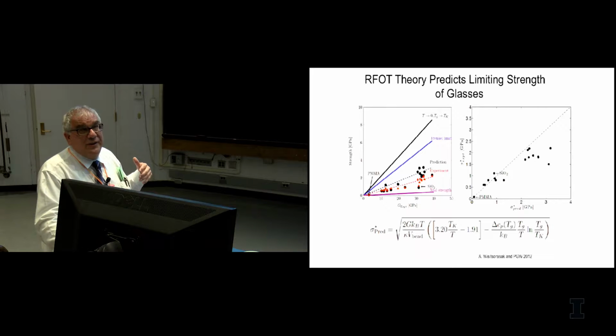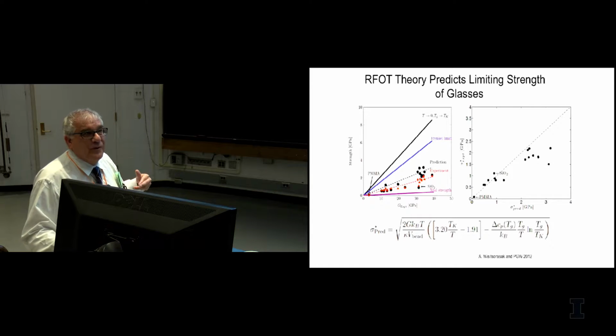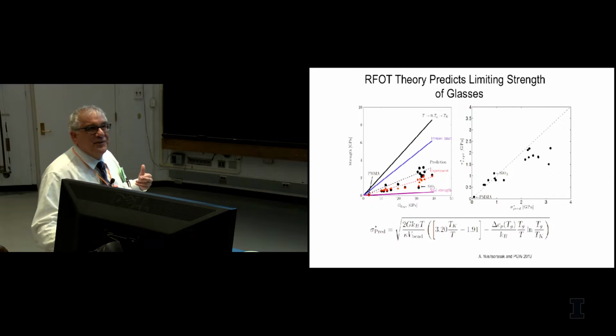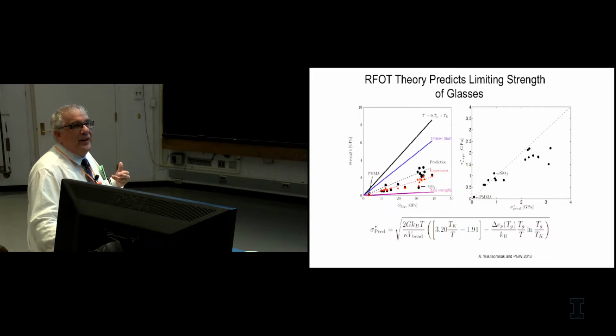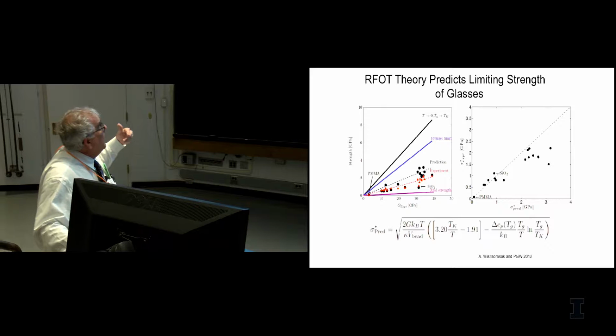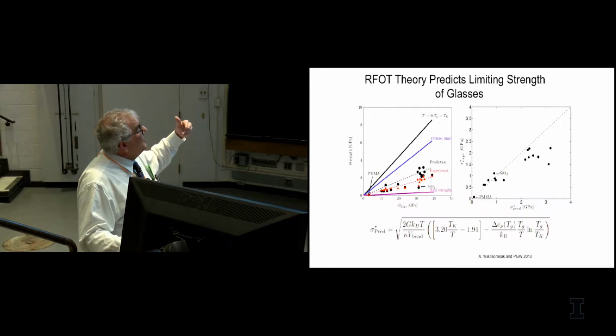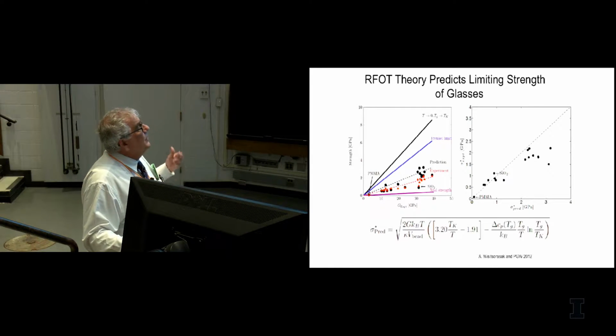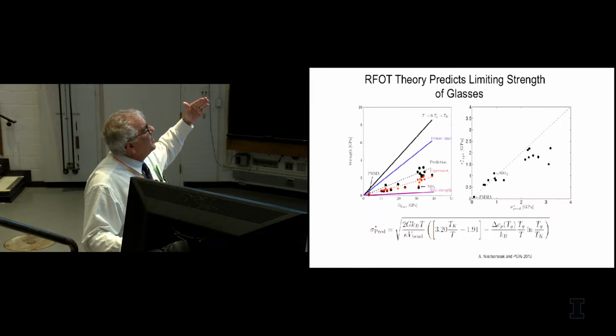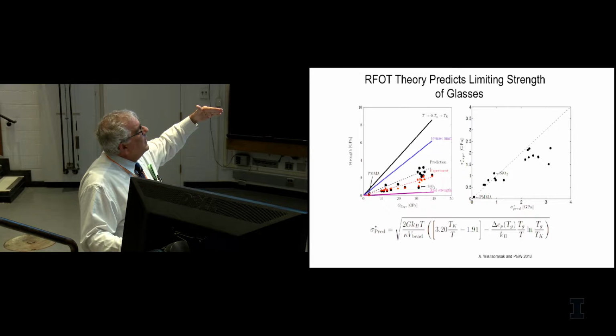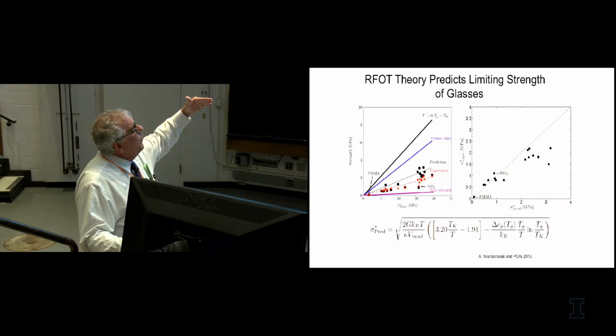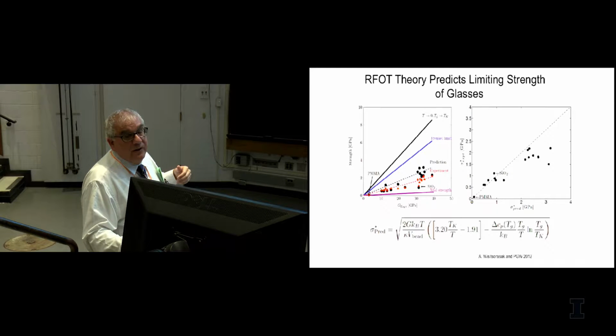Crystals are much less strong than that, like 100 times less strong, which of course led to the theory of dislocations, which I think is one of the great contributions of solid-state physics in the 20th century, I think sadly not recognized by the Swedish people. But what's weird is, of course, a glass doesn't have any obvious places to put in dislocations. And that's why it is much, much stronger. And by this analysis, it goes about 1/3 to 1/2 of the way to the Frenkel limit.